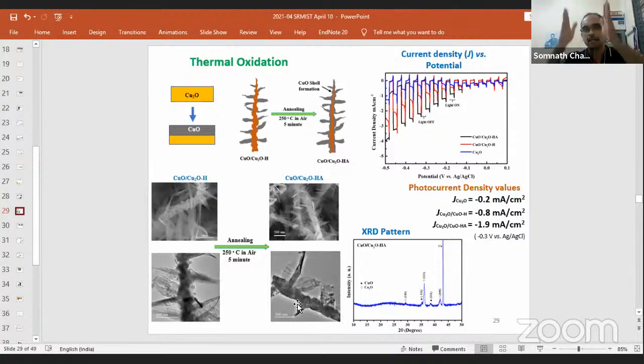Like this main one has grown single dimension, unidirectional, this perpendicular one also grows single dimension. So that's what I call the CuO, Cu2O nanowire nanoflake heterojunction, and with that we got 1.9 milliampere per centimeter square. Now, if you remember two slides back, I boasted about having 4.8 milliampere only from CuO. Then you will ask me, sir, what's so big a deal about 1.9 milliampere, just less than half?